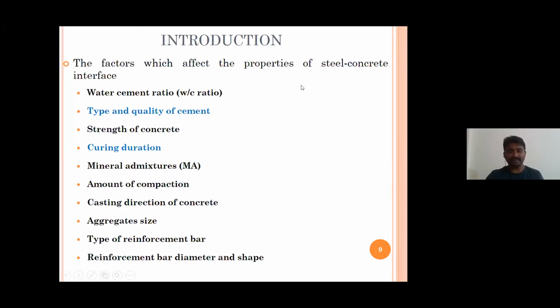So we understood that there are different parameters which will affect the properties of the steel concrete interface. First one is water cement ratio, type and quality of cement, strength of concrete, curing duration, mineral admixtures, amount of compaction, casting direction of concrete, aggregate size, type of reinforcement bar, diameter, shape. All these parameters affect our steel concrete interface. If the water cement ratio is more, people have already predicted, and in our study also we came to know, that the porous zone thickness of that kind of interface will be more.